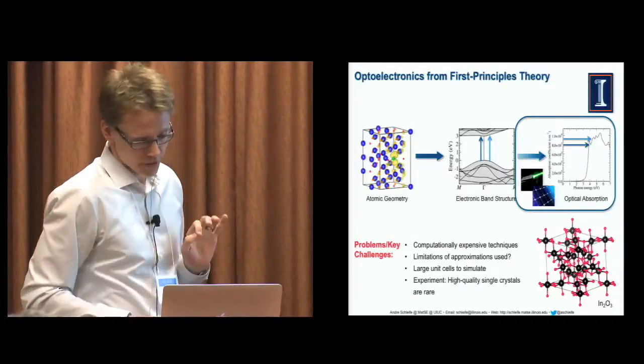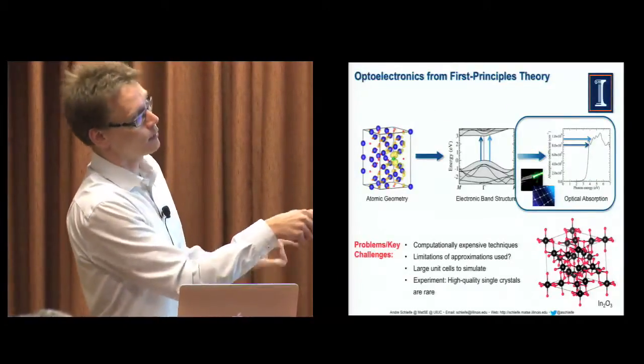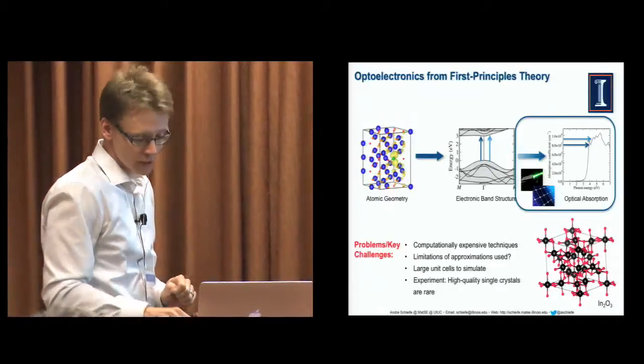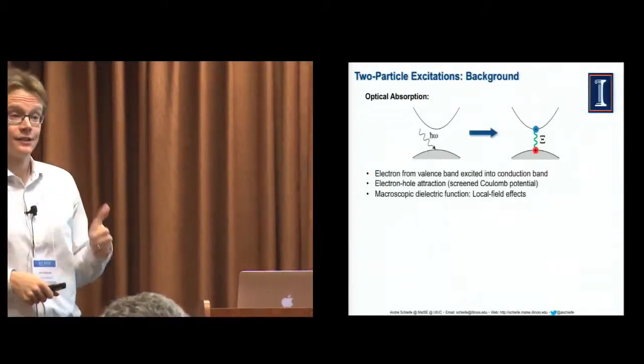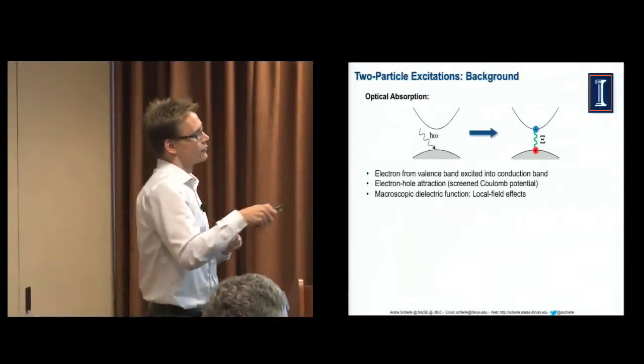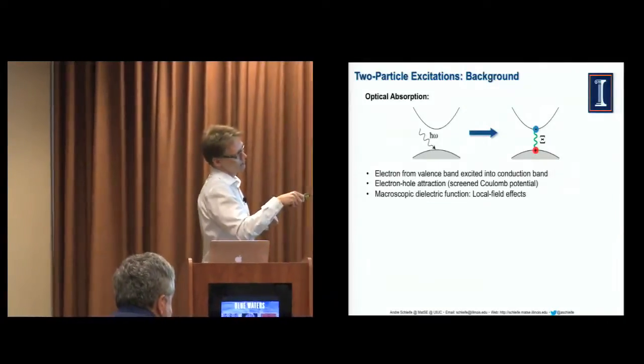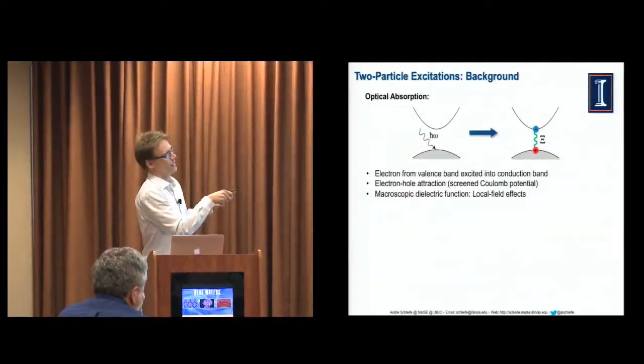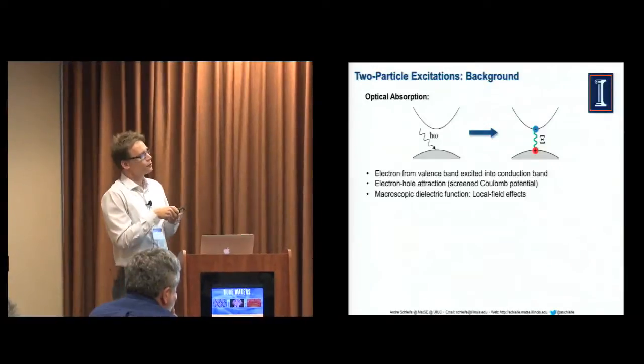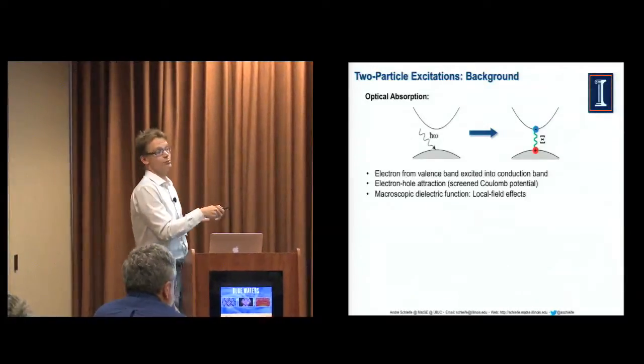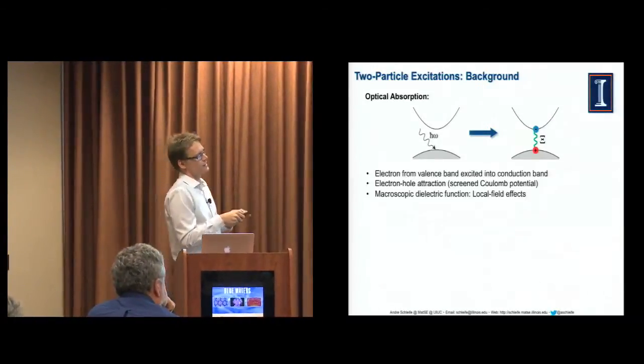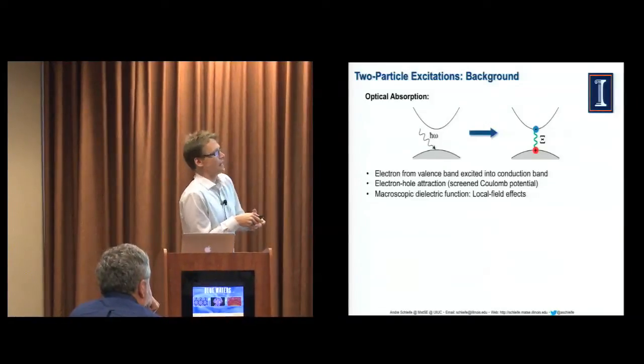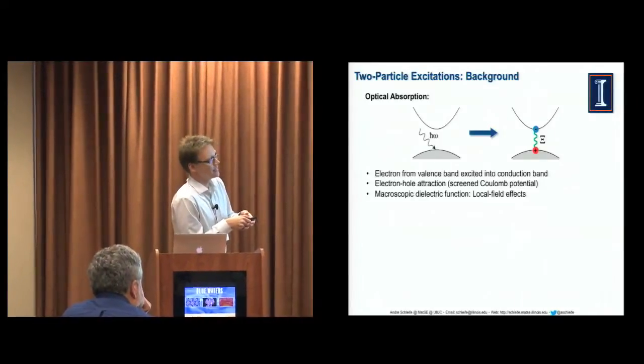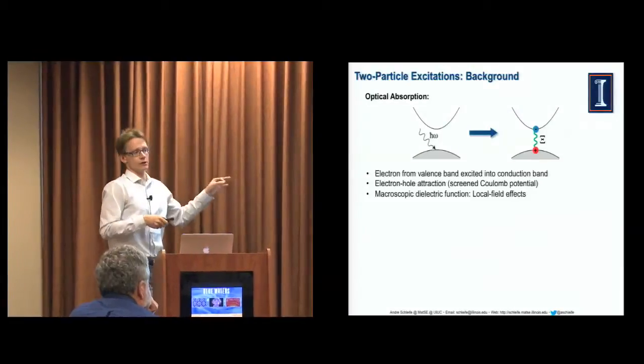Now, okay, so let's assume we have a good band structure. What we now want is optical absorption. The experimental situation is slightly different in that case. So in the experiment, again, we have these bands, right? Occupied valence bands, empty conduction bands, and a photon comes in. Now this photon is not an X-ray photon. We now talk about visible light, for example, right? So in other words, the energy of this photon is much lower, and so the electron will still be in an excited state, but it will not leave the material.